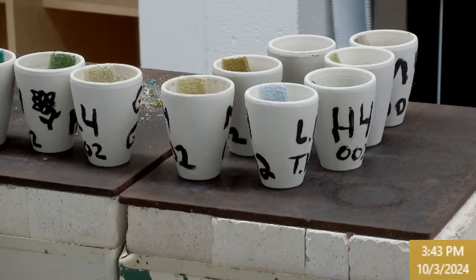And so you could get the same properties if you had lithium the cooler, sodium, and then potassium the hotter. But since we're wanting to compare them all at the same temperature, you end up with a lower lithium viscosity at 1200 or 1150, and then medium and then a high viscosity potassium, because each glass has its own characteristic softening range, where it gets thinner the hotter it gets. It's almost like time-temperature superposition in polymers, except with glass. Yes. There would be some logical tie-ins, the way they overlap those curves and such.